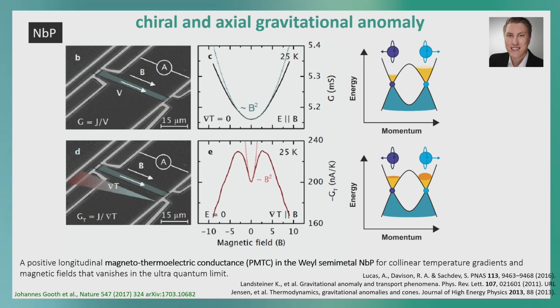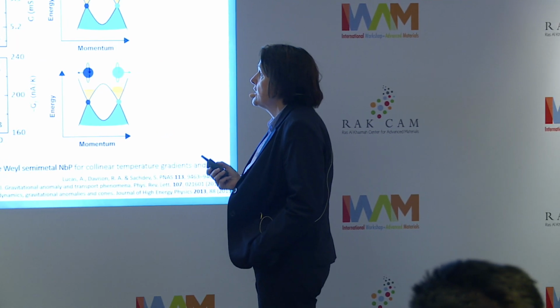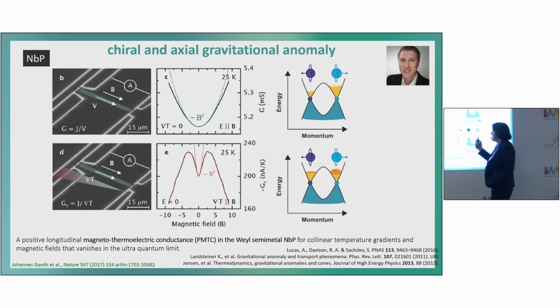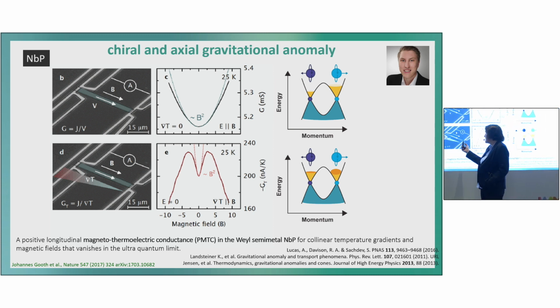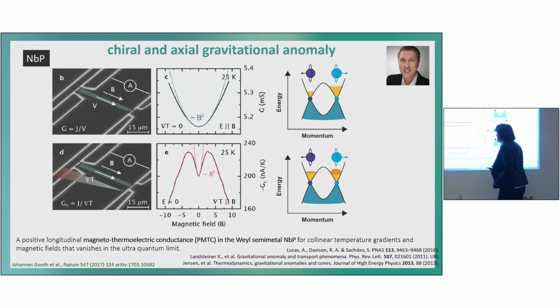So then we looked for the chiral anomaly. We made a wire of niobium phosphide, and we did this parallel E·B measurement. We applied the magnetic field parallel to the voltage, and we saw the predicted B squared behavior in this material. I don't want to go into details, this is simply if you want to ask questions later. Additionally, with the temperature gradient, we saw exactly the prediction that you see this B squared behavior as a function of magnetic field, and then it turns over and goes to 0.